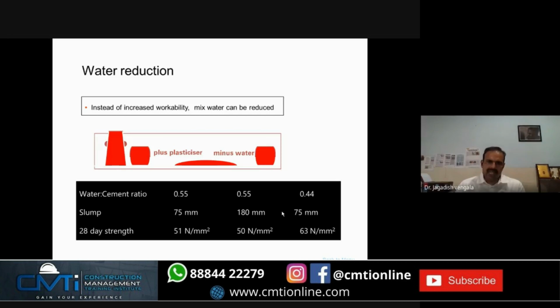So in the first case, by adding superplasticizer, you are getting a more workable mix. That means the slump is increased. In the second case, you are actually reducing the water cement ratio and adding superplasticizer while maintaining the same slump.